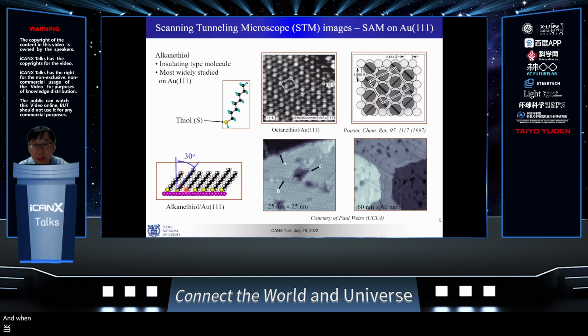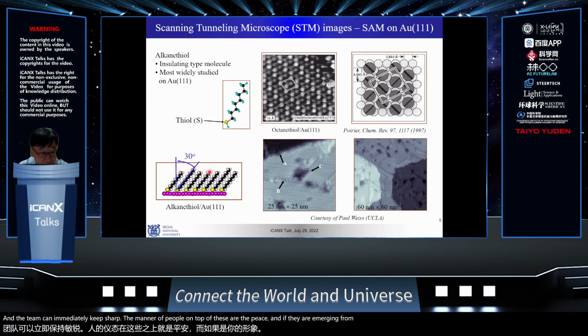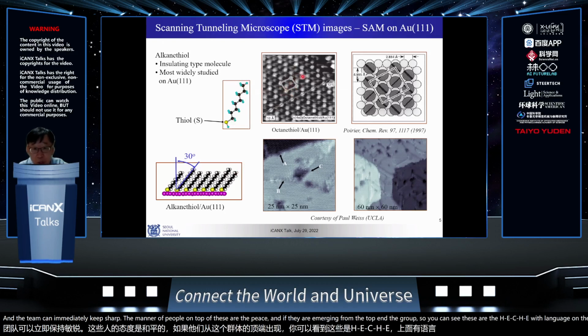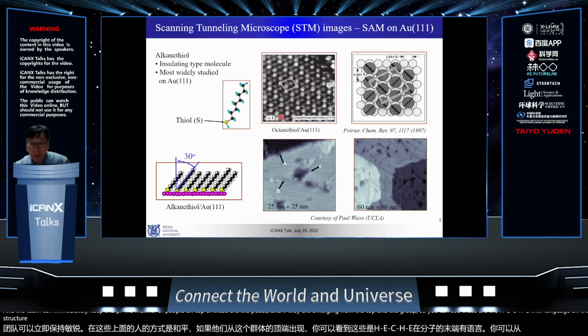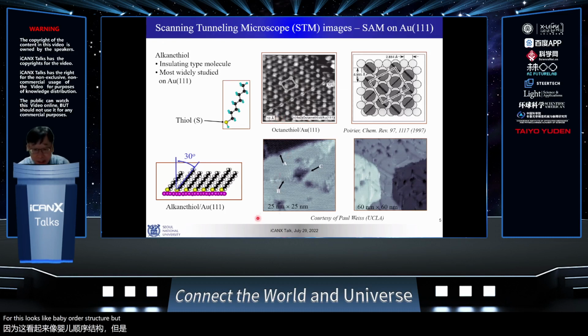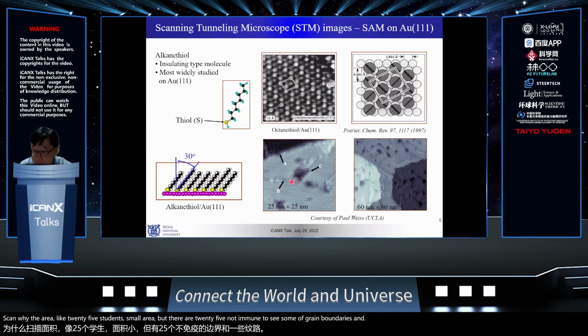When people examine it using the scanning tunneling microscope, you can imagine there's a sharp metal tip on top of this surface, imaging the top end group. So you can see this CH3 methyl group at the end of the molecule, and you can see this ordered structure. But it looks like a very ordered structure; if you scan a wide area, like 25 nanometers, still a small area, you can see some grain boundaries and vacancy islands.